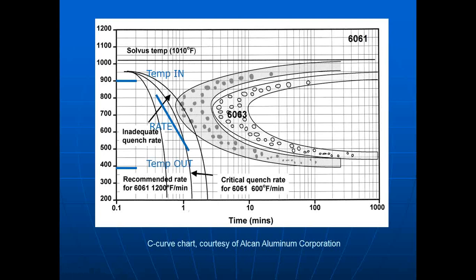Also, if you have internal ribs that can't be water quenched because they're forming hollows inside the profile, those walls cannot be reached for quenching. Only the conduction of the heat through the aluminum cools them. Again, another reason why the temperature out specification may be different for your customer. So those are our three specifications: temp in, rate, temp out. You're going to hear that a lot from me.